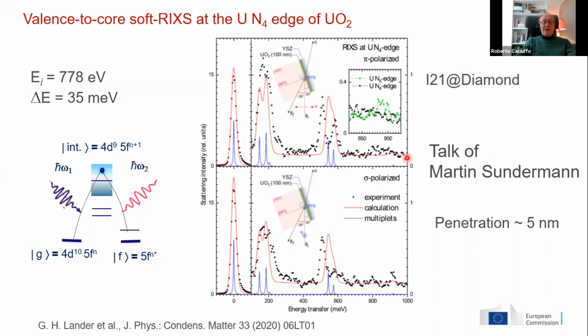In this case, the incident energy is about 750 electron volts. You can achieve a resolution at I21, for instance, at Diamond, of 35 milli electron volts, which is enough for resolving the crystal field excitations in the 5f2 configuration, and to observe intermultiplet excitations. This is, for instance, the transition from the 3H4 to the 3F2 multiplet, which is very difficult to observe with other techniques. Again, the talk of Martin Sundermann will present the results obtained.